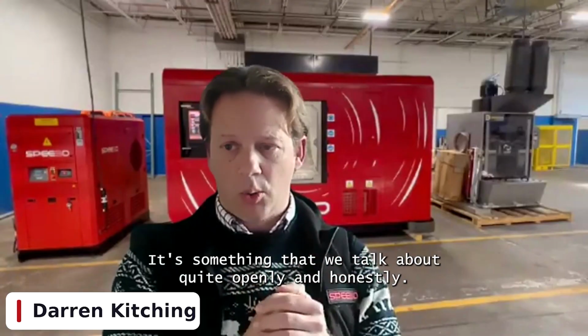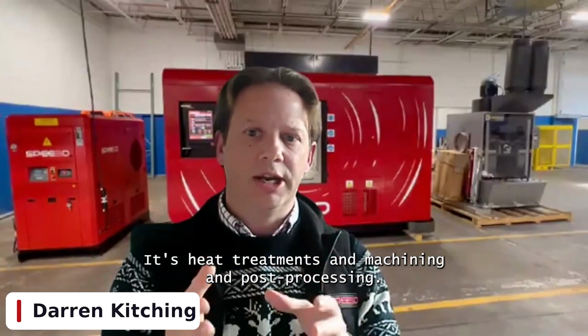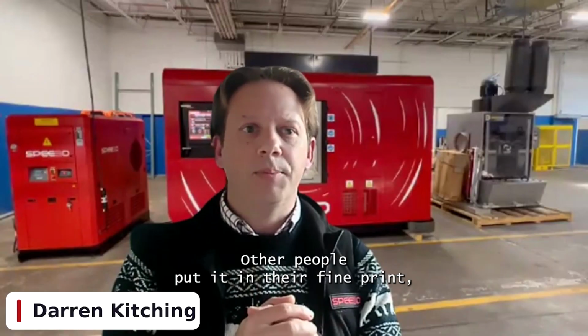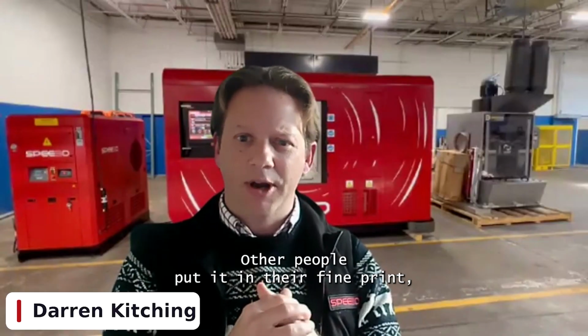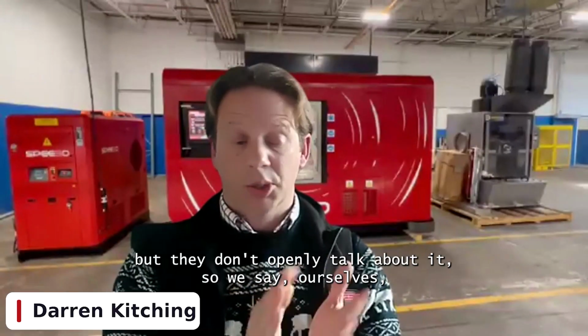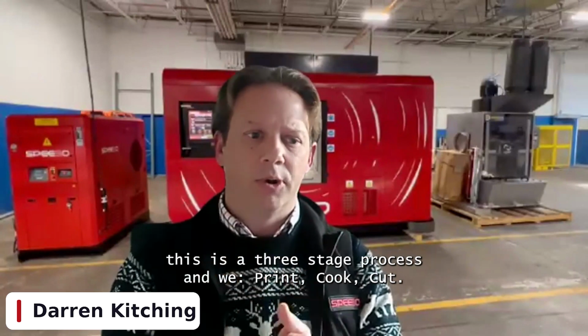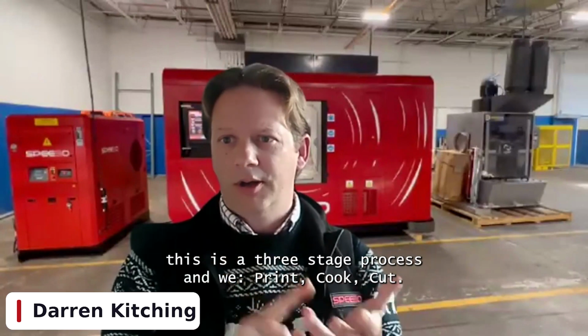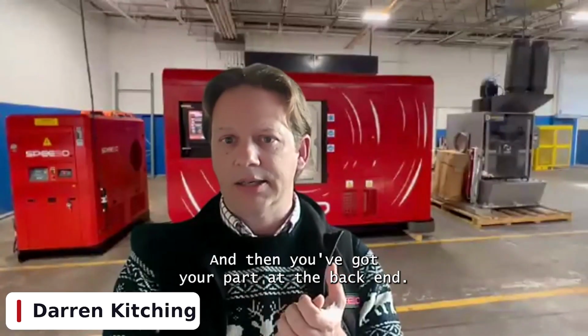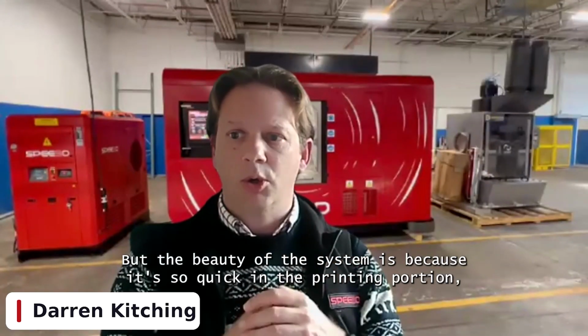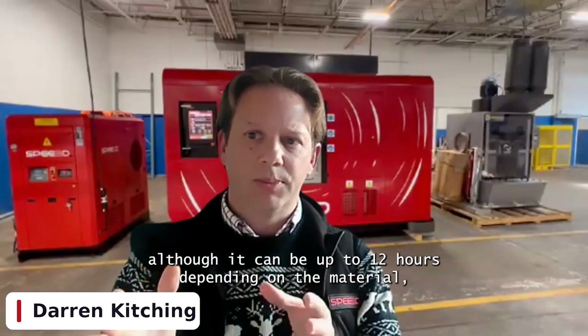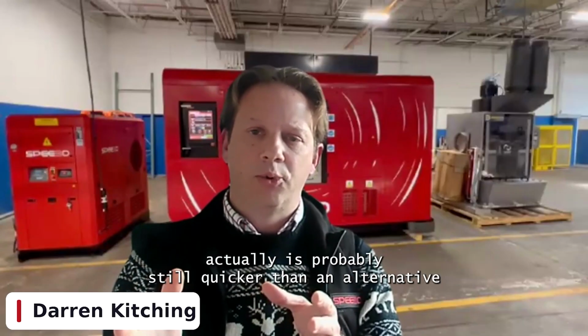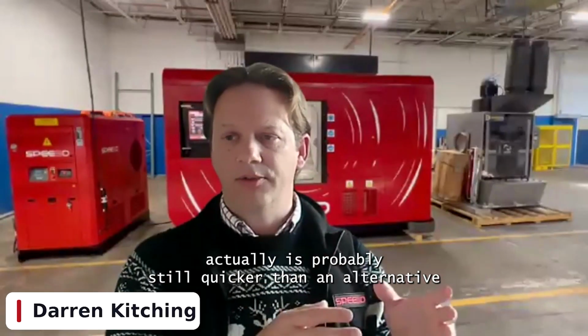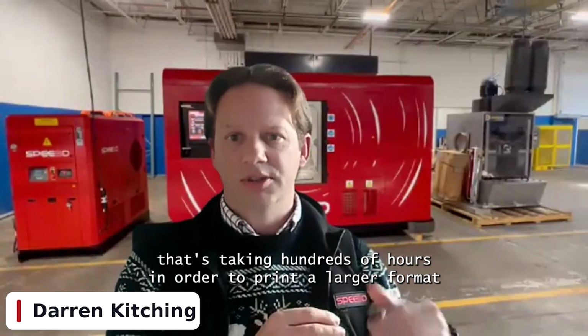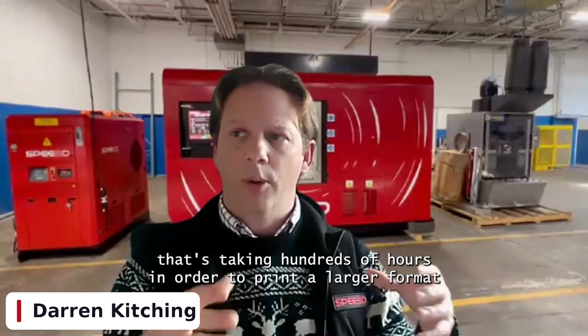It's something that we talk about quite openly and honestly: heat treatments and machining and post-processing. Other people put it in their fine print, but they don't openly talk about it. So we see ourselves as a three-stage process: we print, cook, cut, and then you've got your part at the back end. But the beauty of the system is, because it's so quick in the printing portion, the heat treatment, although it can be up to 12 hours depending on the material, is probably still quicker than an alternative that's taking hundreds of hours to print a larger format part.